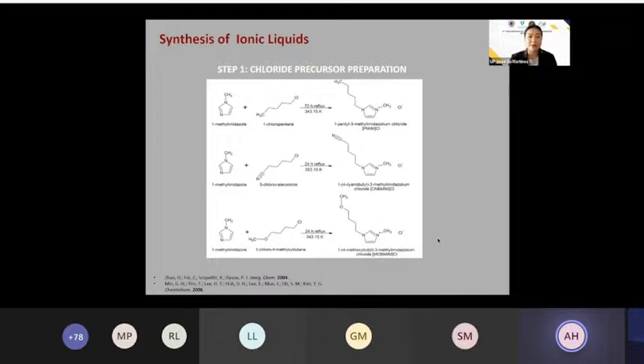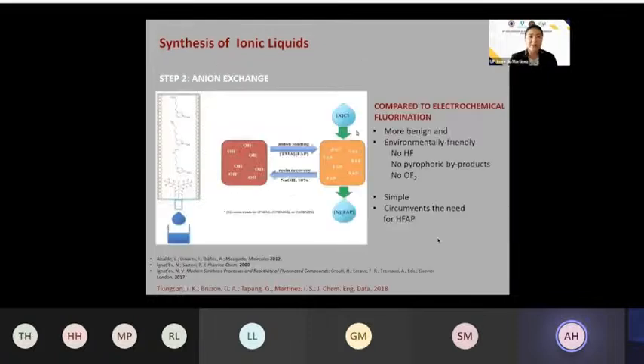So we just follow the same typical steps. First would be the preparation of the chloride precursors, which I have shown here. And then the second step would be just an ion exchange. Like I said, this is more benign compared to the usual electrochemical fluorination method, because you don't produce toxic compounds such as HF, pyrophoric byproducts, and there's no OF2 produced during the synthesis. It also circumvents the need for HFAP.